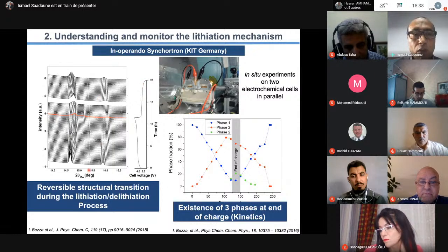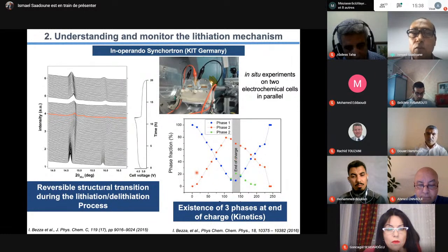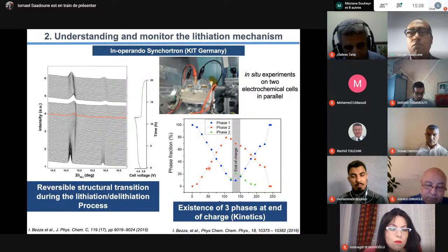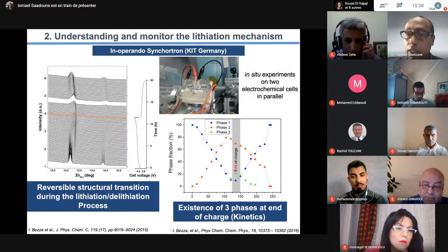And you see we follow the charging process and the discharging process in-situ, and we try to calculate the unit cell parameter. Normally we should have one phase, maximum 2 phases, during charge or discharge. But in some cases, we get 3 phases. This means that we have some kinetics problem, which is normal in phosphate, where we have low conductivity in the particle.